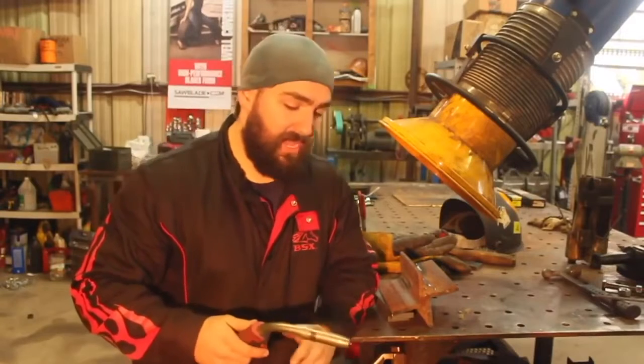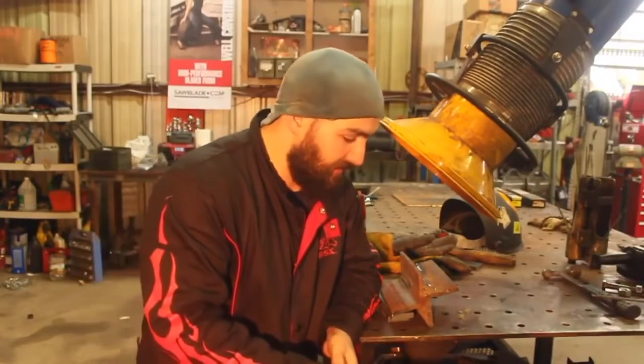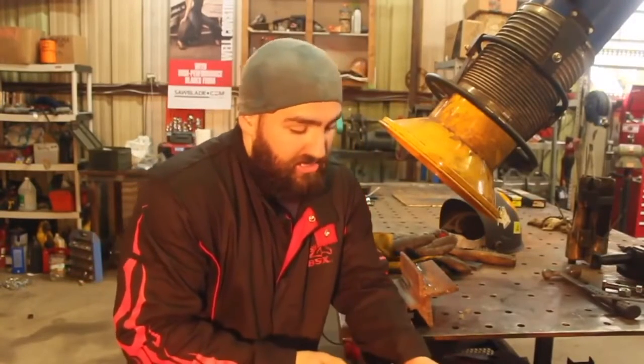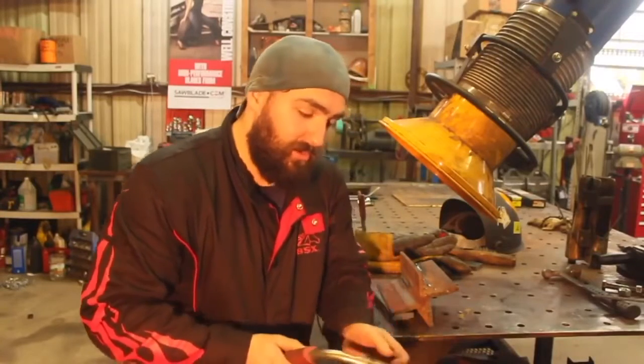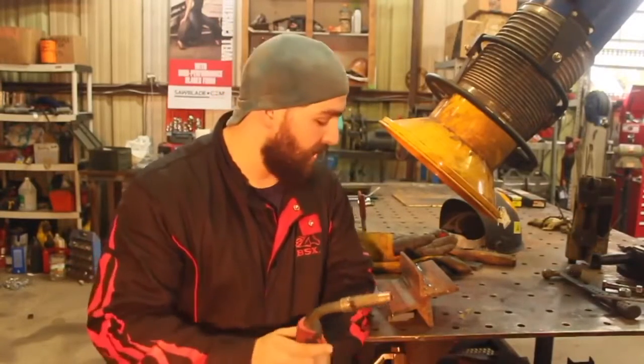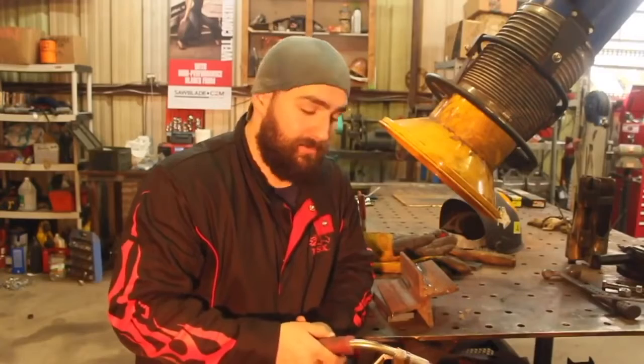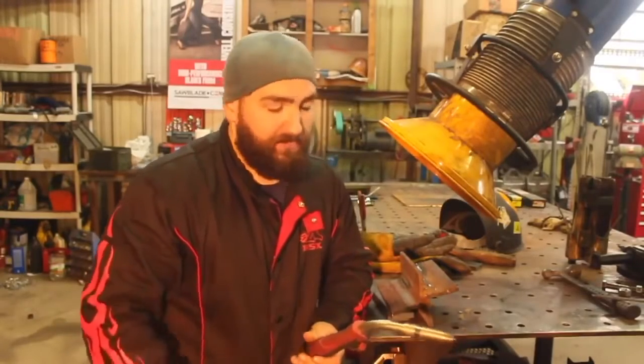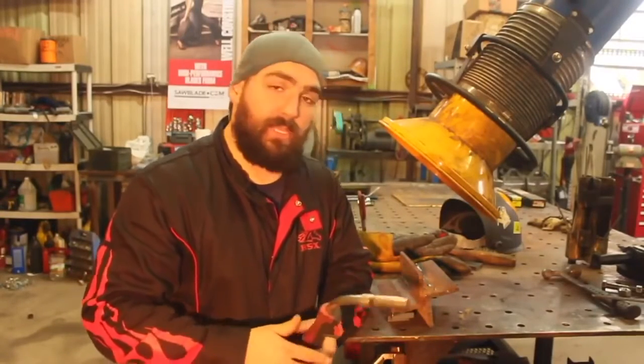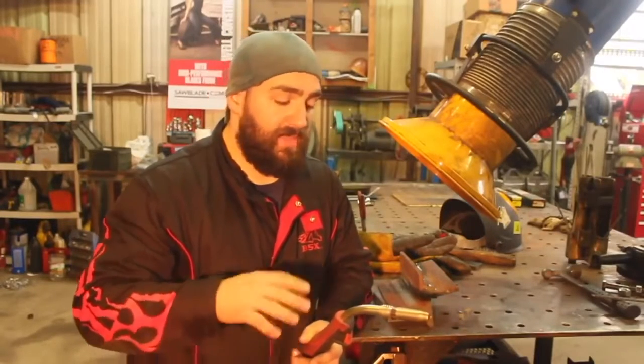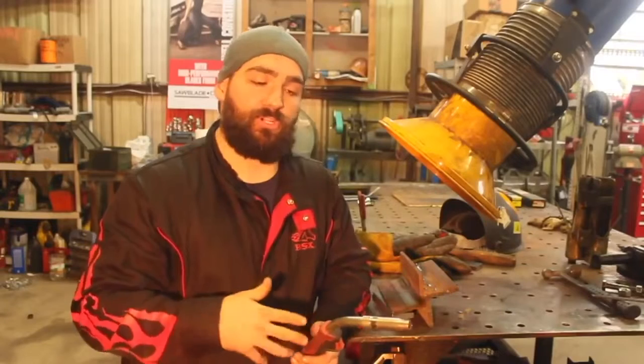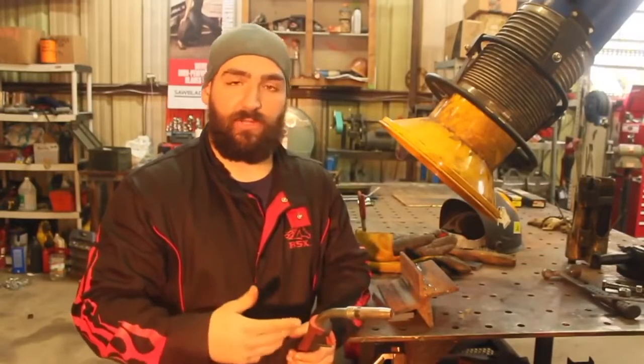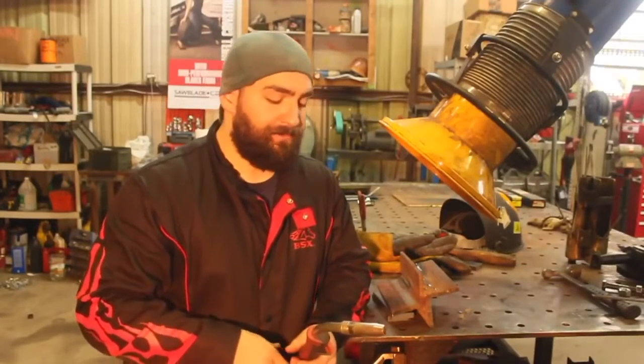Similarly, if you take that nozzle and you've got it in a really tight spot and you're just a little too far away, it's going to do the same thing. Or if your flow rate is too high and you bury the nozzle too close to the metal, you can blow that gas away. So there's a couple things that can cause wagon tracks, wormholes. Those are all surface porosity things that can be tweaked just by paying attention to what you're doing, looking at your machine and your equipment, and diagnosing that.